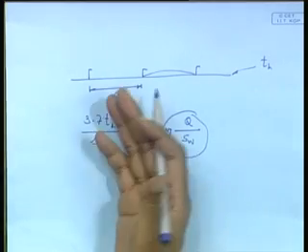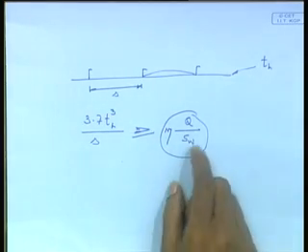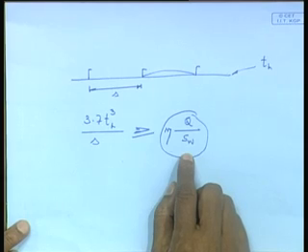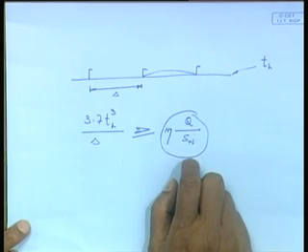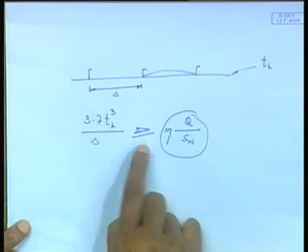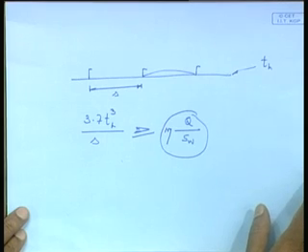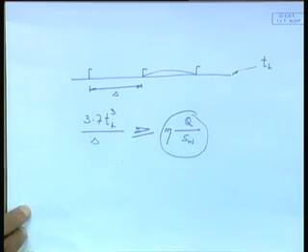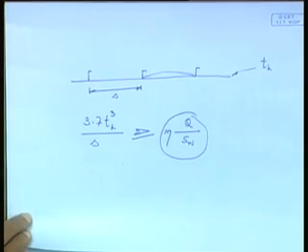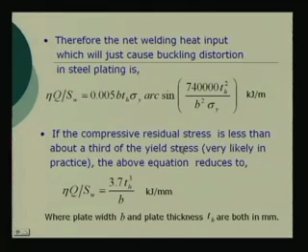So, this gives me a very easy factor through which I can calculate and then check with the welding Q, SW I have worked out, such that that figure remains less than this figure. Then I can say, well, the possibility of buckling deformation is less, because if buckling deformation takes place, it is very difficult to remove that. So, one tries all means to control and prevent buckling deformation.